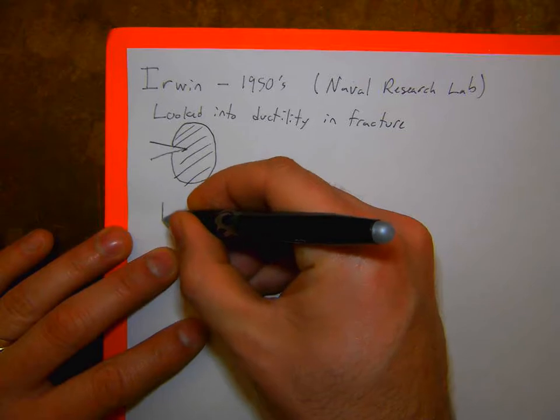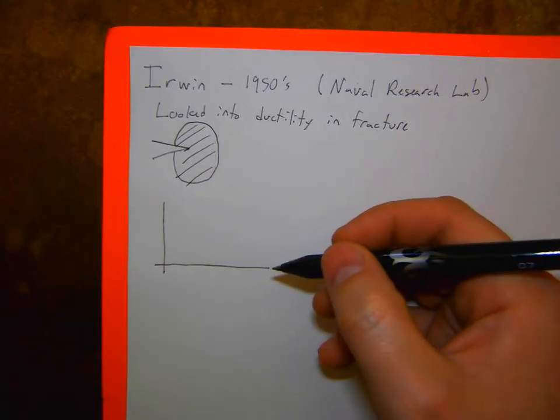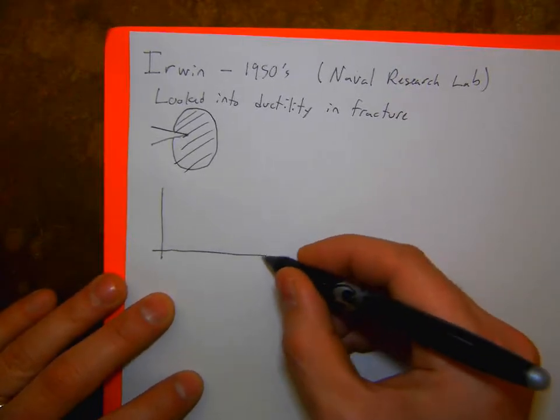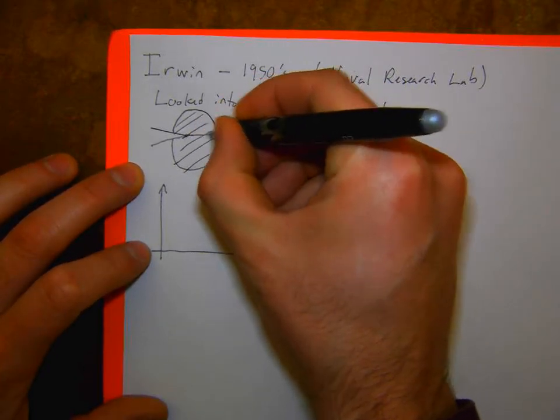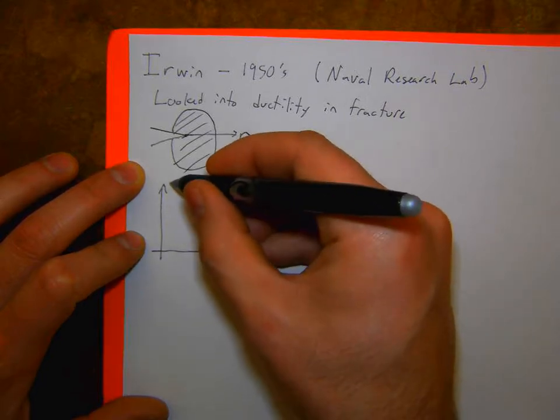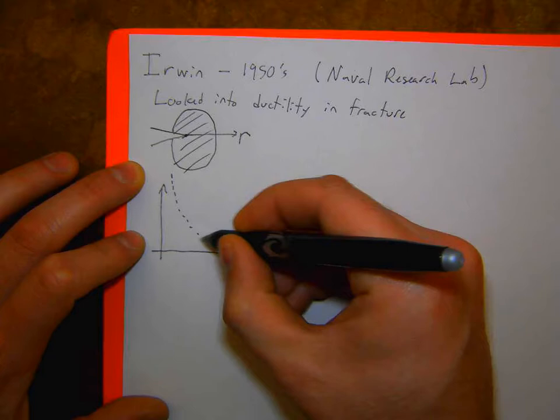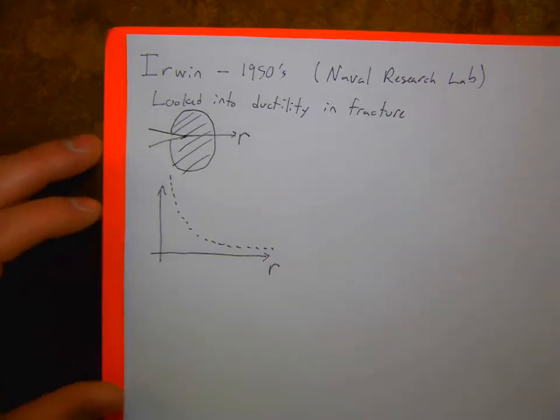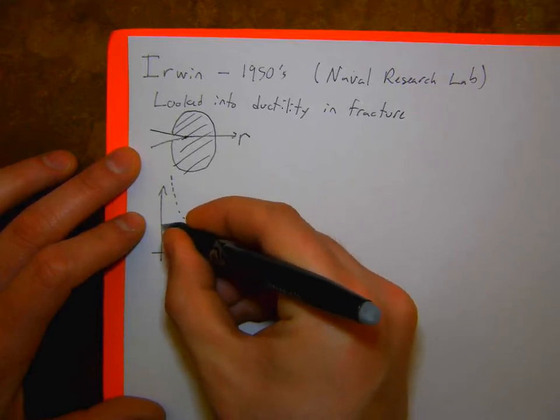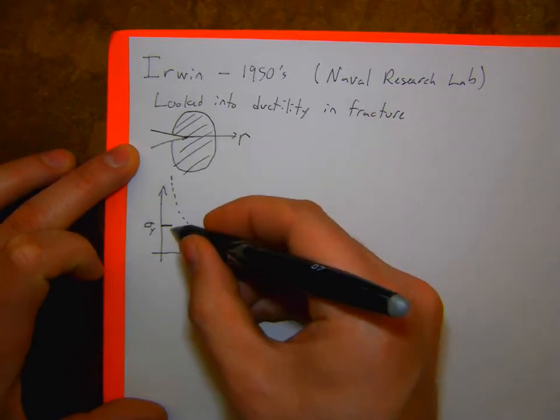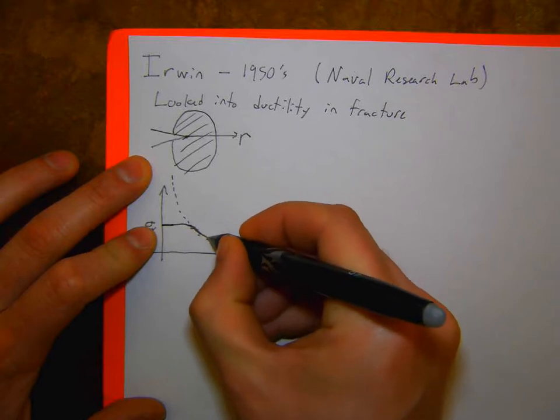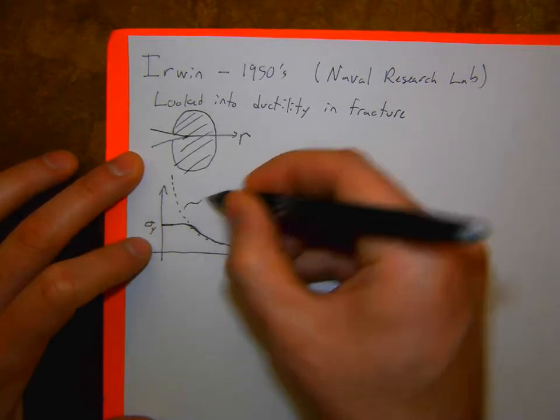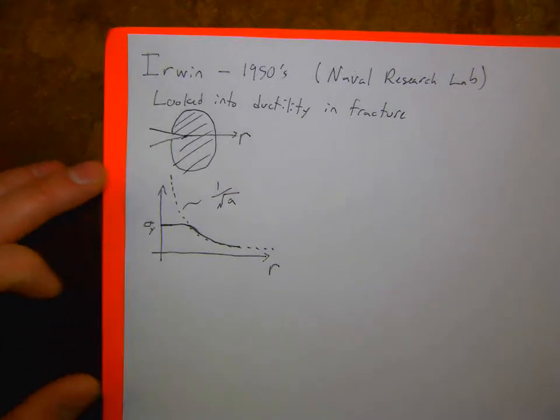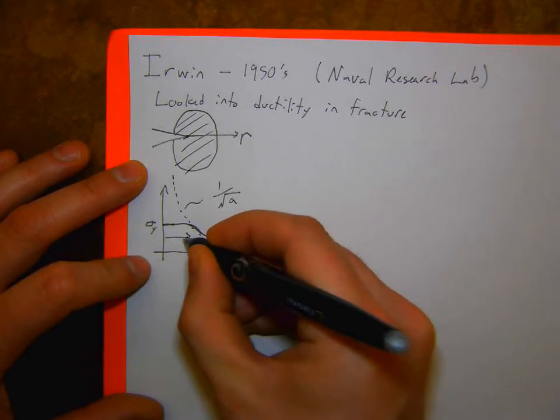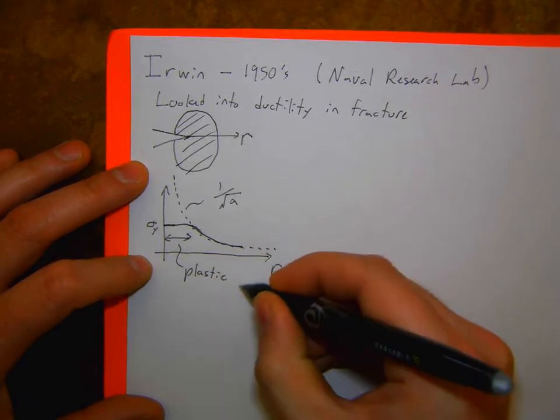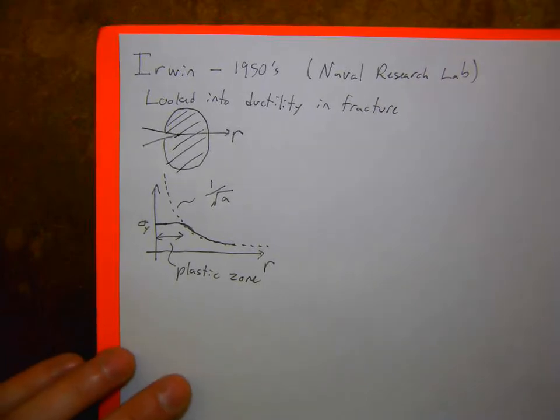But what he started to see was that from that Griffith theory, we expect now the stress near the tip of the crack, from the tip of the crack going out some distance, we expect a 1 over square root of r dependence on the stress. So we expect that stress to kind of go up exponentially, but that's not actually what happens. In reality, there's some plastic yield strength near the crack, and then that will start to decay out until we get to a far field stress, and then it'll start to actually approximate this 1 over square root of r dependence on the crack size. So here now, to actually account for this plastic zone, what he did was he took Griffith's theory and he started to modify it.